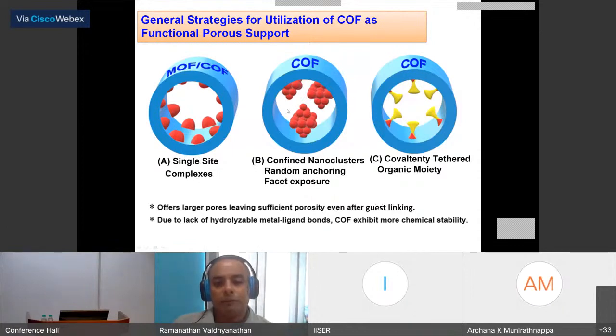And in the same way you can develop small nanoclusters of very redox active metals inside the COF confinement, and this will also help you expose the facets of the nanocluster which are not otherwise easy to expose in a capped surfactant-based mode. And this makes a COF an excellent porous support for anchoring nanoclusters with high activity. And the third approach can be linking covalently organic functional groups onto the walls of a COF, either during synthesis or post-synthetically, and then you can use them very efficiently as binding groups for a variety of guests.